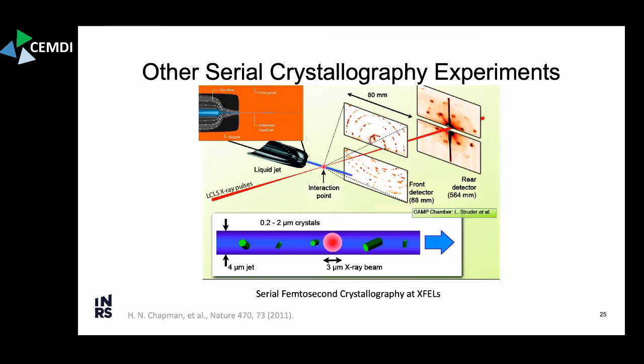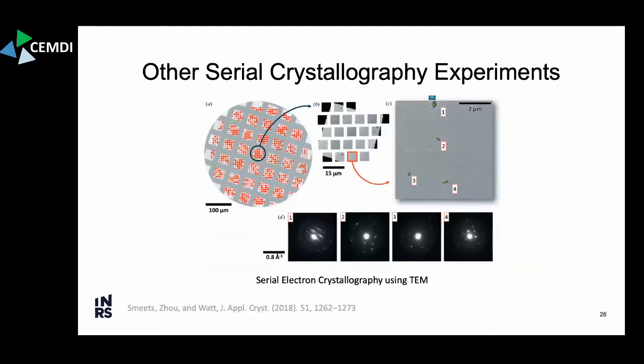This isn't the only way to do serial crystallography. I was also involved in doing it at X-ray free electron lasers. And there you have the issue where you destroy the sample due to the high intensity of the X-ray beam. And so instead of translating on a Kapton tape, we streamed the sample in a microjet. We just streamed our crystals in a microjet and collected diffraction patterns on a series of detectors.